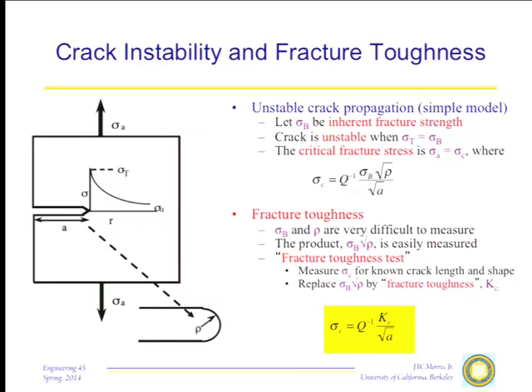That says that what we really care about is what is the value of the applied stress, the nominal stress, the overall P over A on the sample when the crack goes unstable. So I want to know what is the value of sigma A when sigma t is equal to sigma b. So I just plug in the equation on the last page and I solve for that, and I get that the breaking stress, and we call this the critical stress sigma c, that's the value of the applied stress when the crack goes unstable, is equal to Q minus 1, that's a geometric factor, I'm not going to spend much time talking about, depends on the shape of the crack geometry, times the breaking stress, times the square root of rho divided by the square root of A. And this is my measure of the critical stress, the stress at which this crack's going to go unstable.